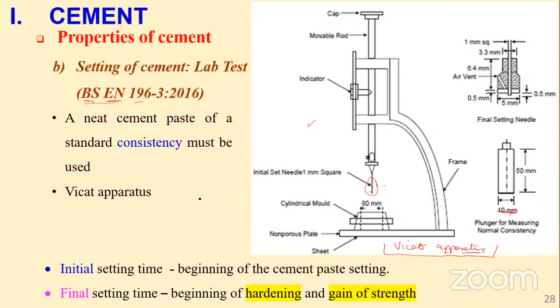Now, for you to determine the setting time of cement, you conduct the setting time test on a cement paste of some consistency. So again, I introduce a certain term. You want to do a test on cement paste, but it's not just any cement paste. Anybody can prepare a cement paste, but we are saying there is a certain criteria or classification for a cement paste that we need, so that now we can say this is a standard sample, we can do a test on it. So for that standard sample, we require a cement paste of standard consistency, or what we call normal consistency.